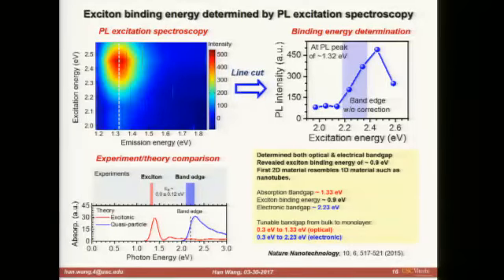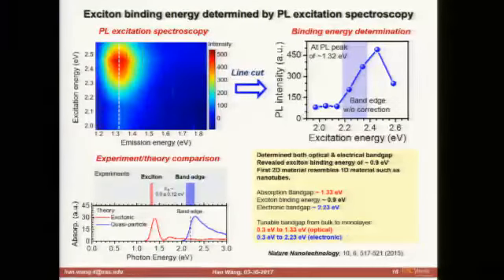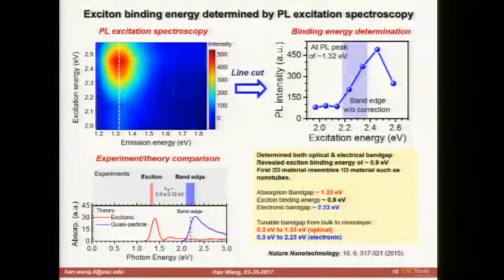Another important result from this study is that this is one of the first measurements, the first experimental determination of the optical band gap in single atomic layer black phosphorus, and also the exciton binding energy. The absorption band gap is around 1.33 electron volts. The exciton binding energy is pretty large, 0.9 electron volts, but that's on the same order as materials like molybdenum disulfide. Also, the electronic band gap, or quasi-particle band gap, is 2.23 electron volts.